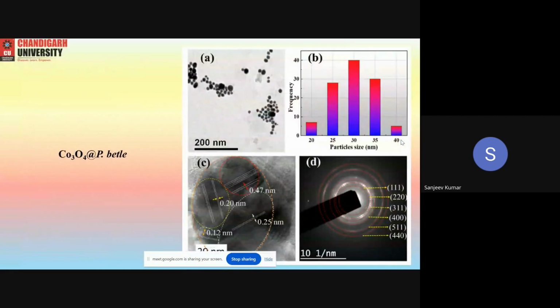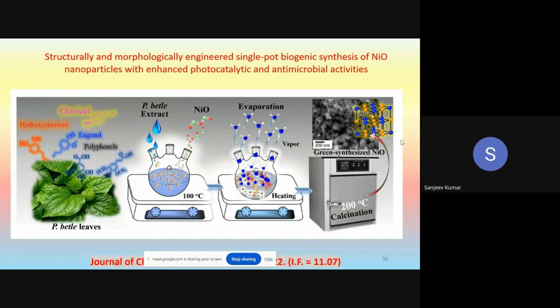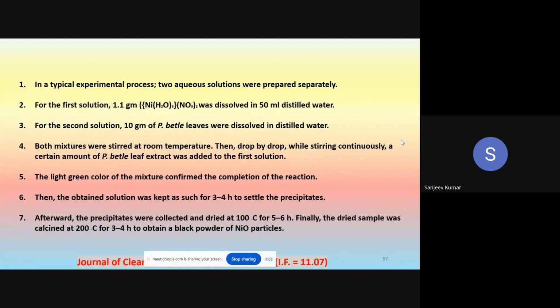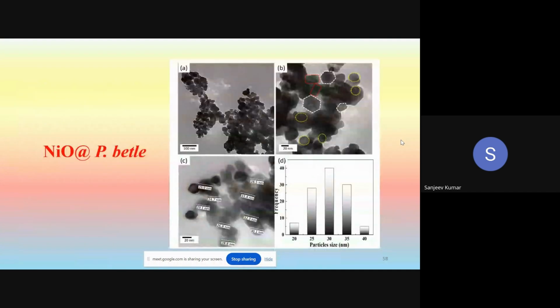This is typical, and these are some of the particles which we have obtained using piper betel. Once again, the shape is beautifully controlled. You can see the size range of the particles is in the 30 nanometer range. This is the pictorial view. Once again, we have synthesized this using the chemical precipitation technique. This is one of the typical recipes to synthesize these nanoparticles.